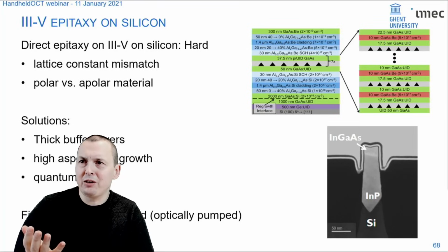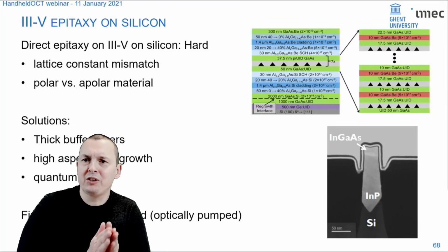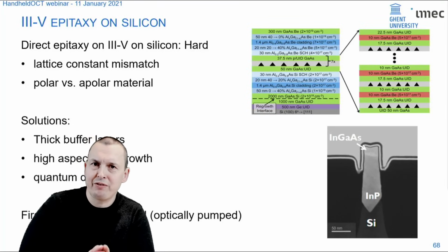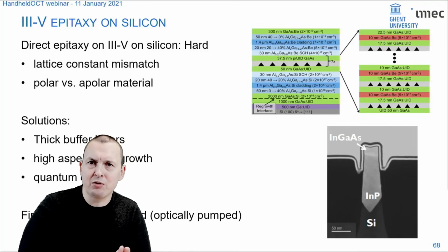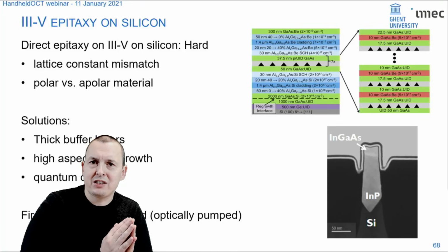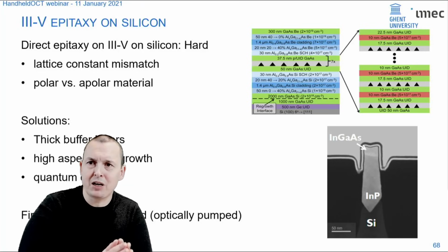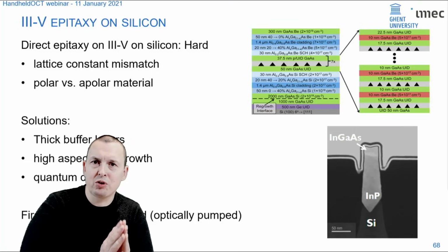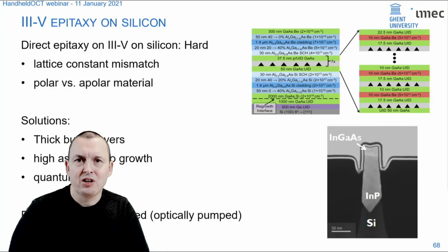The holy grail where people are moving towards at the moment is to epitaxially grow the III-V semiconductor in your silicon photonics. Just like they epitaxially grow the germanium, now grow III-V semiconductors. That's far from trivial, and there's already a massive amount of research invested in this, but we're going in the right direction, with already first demonstrations of lasers in the silicon photonic platform, epitaxially grown.